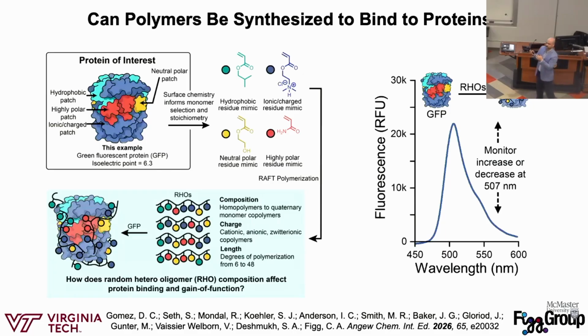And how do we actually study which ones are the strong binders versus the weak binders, or the winners versus the losers? One of the reasons why we like green fluorescent protein is that you can monitor the fluorescence of the protein pretty readily. We know this is not the case anymore, but in the initial experiments here, we assumed that fluorescence was going to be a direct readout of binding. So if we're getting a fluorescence increase, that's an indication that the oligomer is binding to the protein and making the protein more fluorescent or work better than it does. Or you can think about denaturing, where it's still binding, but we're denaturing the protein. So we get a direct readout of what the oligomer is doing to the protein just by monitoring the fluorescence of GFP.